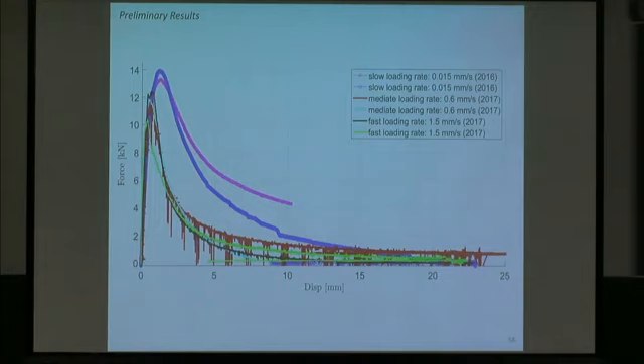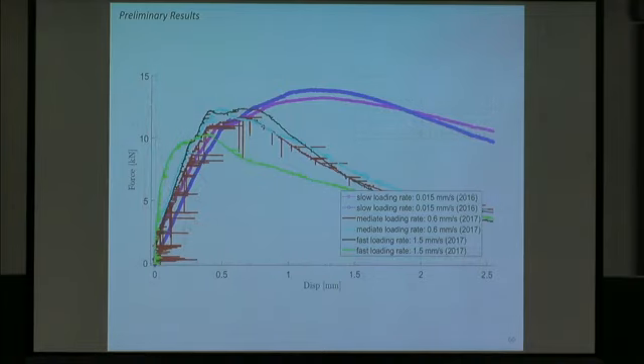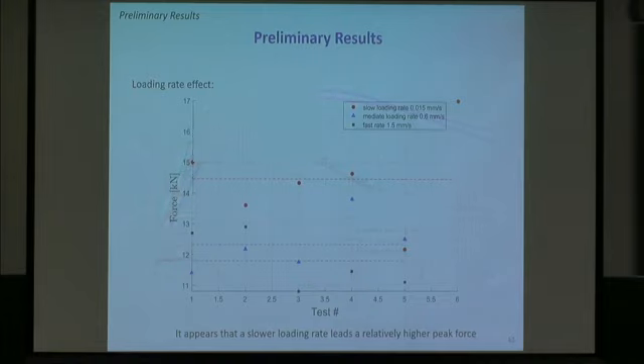And the question here is, are we able to describe this loading path with linear elastic fracture mechanics? At first look, it looks okay, but if we zoom in on this part, we see that it's really kind of curved. And whether or not we can use linear elastic fracture mechanics, I don't know yet, but it doesn't look perfectly linear going up. And also we see that there seems to be a loading rate dependence on the peak force. That's a bit puzzling to me. I don't understand why if we load it slow, we get a high peak force. If we load it relatively fast, we get a low peak force.